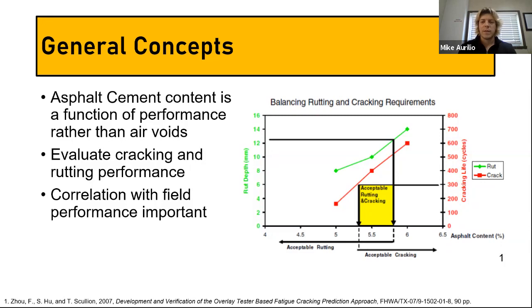And in that system, the asphalt cement content is no longer a function of the air voids, it's now a function of the performance. So you perform a cracking test and a rutting test. And in some cases, you can prefer one or the other, but for this example, you perform both tests. You test the mix at 3 different asphalt cement contents, and you can see from this graph that the rutting performance and cracking performance obviously change with the asphalt cement content.